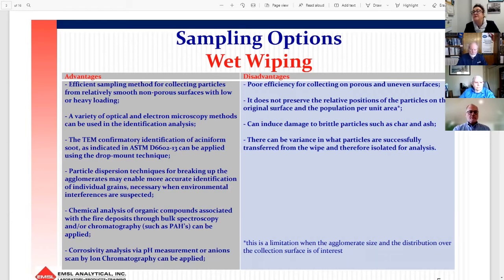It has a poor efficiency, again, for collecting on porous surfaces, uneven surfaces. It definitely does not preserve the relative position of the particles on the original surface or the population per unit area. The same thing, it may induce damage to the brittle particles, such as char and ash, and there may be a variance in how you extract the particles from the wipe into the suspension for the analysis. So all these are things to take into consideration when you decide what sampling technique to use.